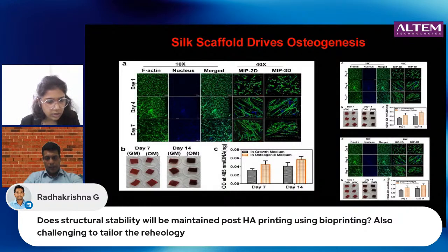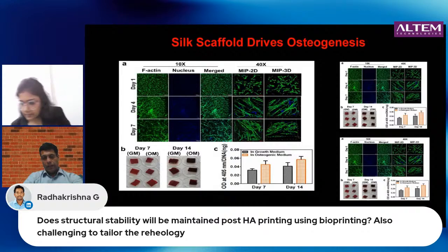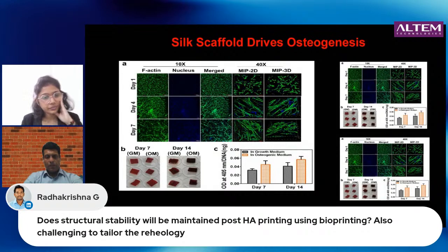Yes. So here, I should mention that in our case, we haven't done bioprinting with HA, because the work I showed you was printing PLA and then putting HA on it, and then seeding the cells on it. So that technically isn't bioprinting, it's 3D printing, but the properties of the scaffold didn't change much, because the bulk of the polymer wasn't affected. It was only the surface that was getting affected. If talking about rheology, that didn't matter, because it's post printing that you're doing things.